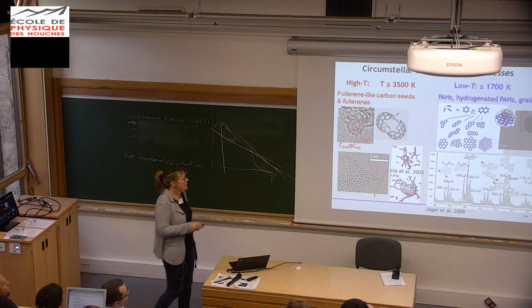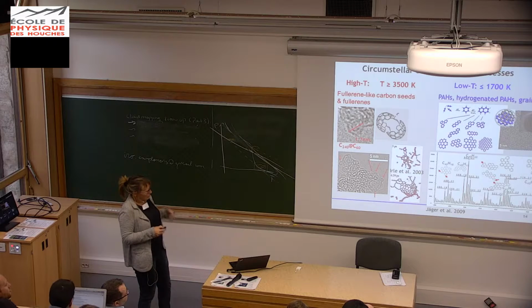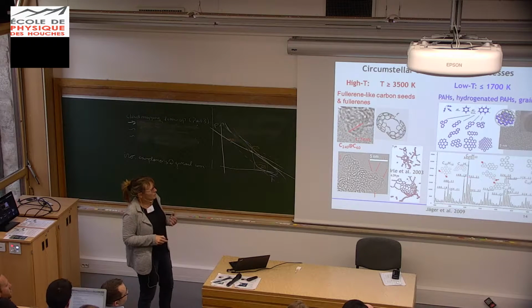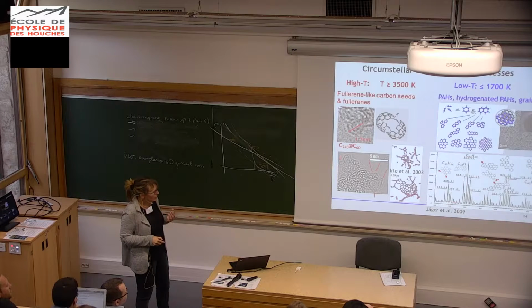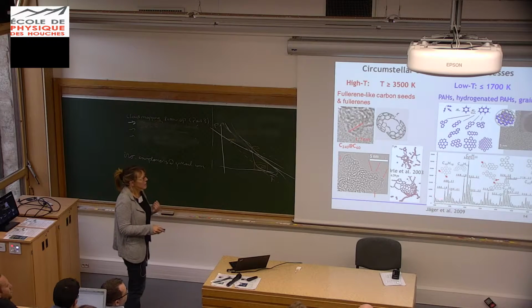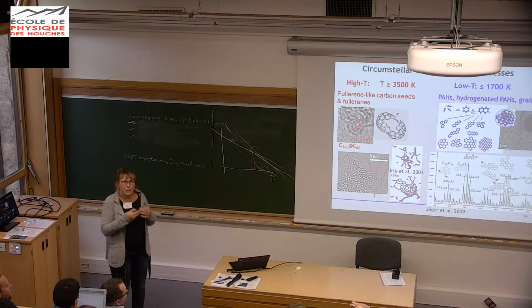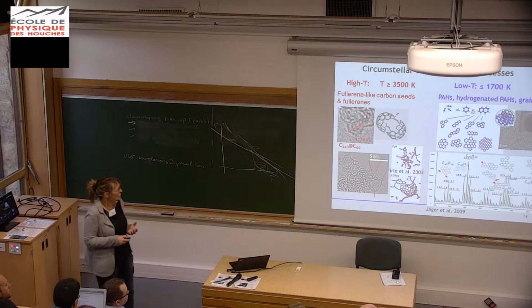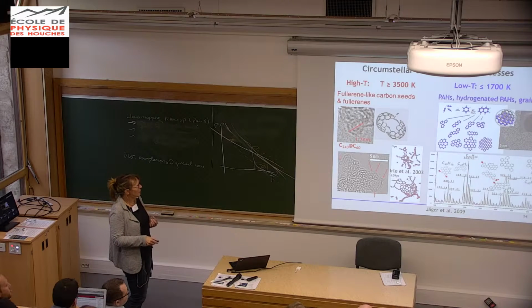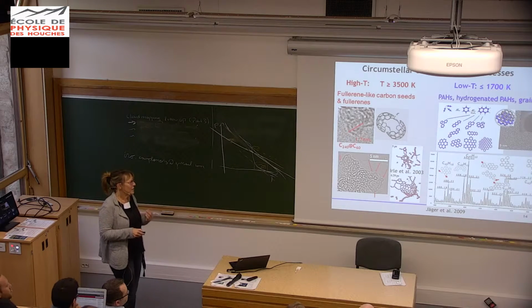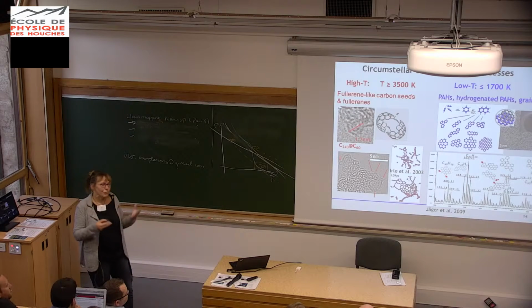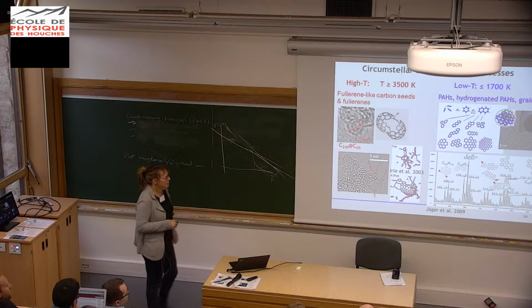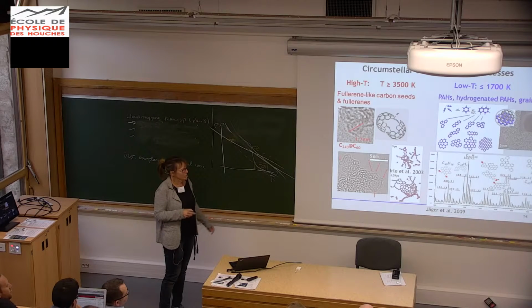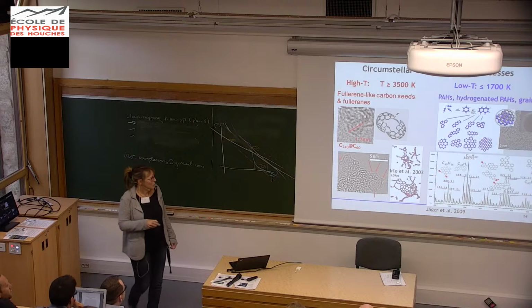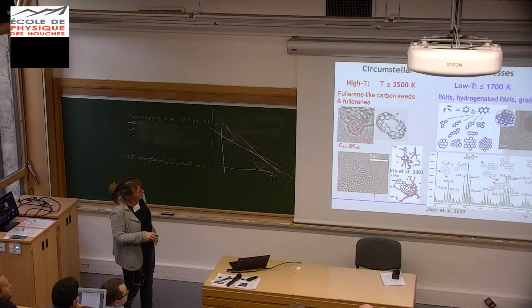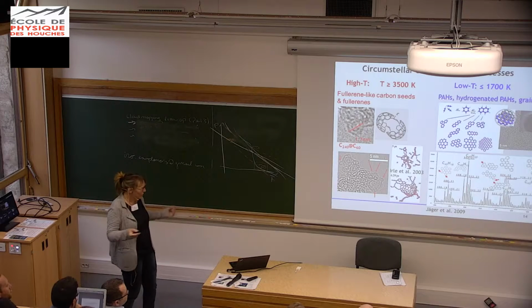If you look at these condensates much more in detail, for example with high resolution mass spectrometry as shown here, you can see that you produce a very huge variety of different PAH material. You produce really every mass and every isomer you can imagine, up to masses of, let's say, 3000 or even higher Dalton. The sizes of these PAHs really vary from very small up to very large.